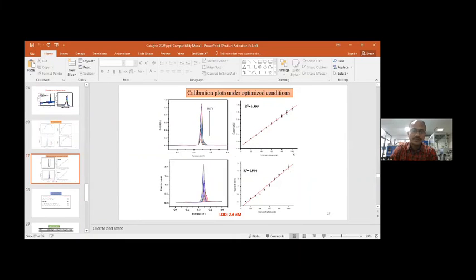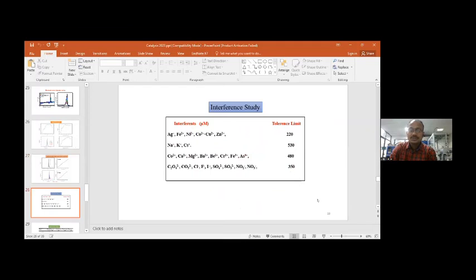Of course, not only mercury, we can take other analytes also, that is lead, cadmium, as well as copper. We have done the calibration plot under the optimized conditions, and we got 2.3 ppb in the presence of 10 to 100 ppb of mercury. Again, we did an interference study, as we know that before going to application studies, we should check the selectivity of the modified electrode, whether it is suitable for mercury or affected by any other analytes which will be present in the samples. We tested almost all cations as well as anions, and the modified electrode did not interfere with these ions. So we can say that the modified electrode works very selectively towards mercury.